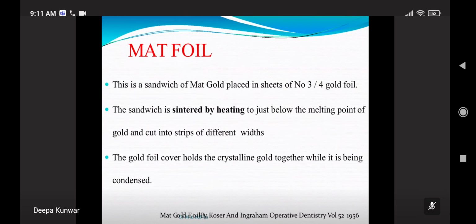Okay, this is a sandwich of matte gold placed in a sheet of number 3 or 4 gold foil. Either number 3 or number 4 gold foil is taken. When we take out the precipitated gold from normal foil, that is matte gold, and if we place that matte gold into the gold foil, that is either the number 4 or number 3 sheet, then it will be matte foil. Okay, the sandwich is sintered by heating to just below the melting point of gold and cut into strips of different width. The gold foil cover holds the crystalline gold together while it is being condensed.